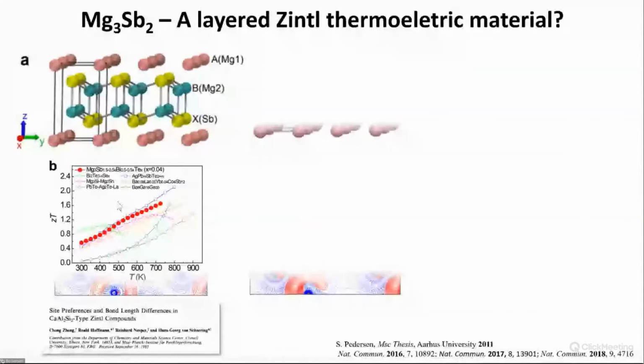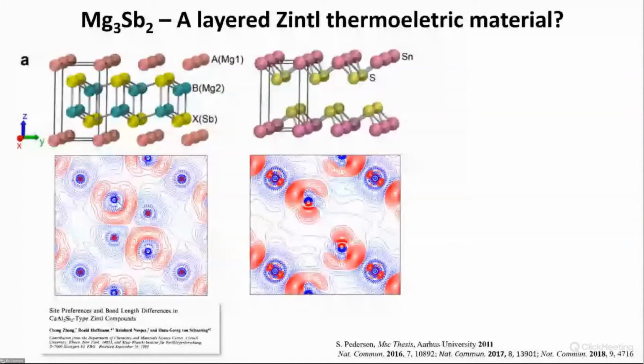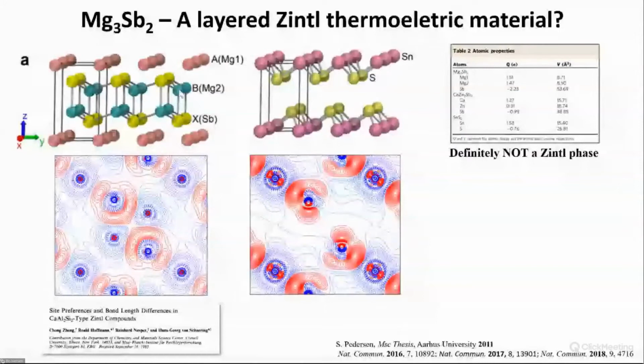But if you then go and actually measure the electron density here, for comparison I've taken tin disulfide. It could be titanium disulfide, as you saw before. Here you have the van der Waals layer, so basically it's the same structure. You just added these magnesium 2 cations into this layer. And when you do the electron density and analyze the chemical bonding, you'll see that the 2 magnesium atoms in the structure are virtually the same. So they have approximately the same charge. The chemical bonding is kind of the same. So this is clearly not a Zintl phase, this magnesium antimonide.